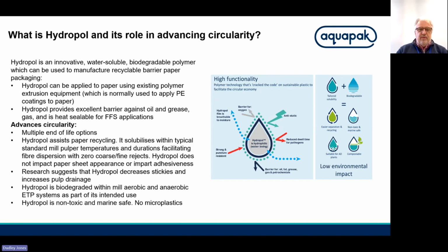So the tests have been done. I'll talk to you about that in a minute. But basically, it solubilizes in the typical pulper temperatures and durations. So within 10 minutes, it basically breaks down and it facilitates fiber dispersion. So you get a cleaner fraction when Hydropol and paper are put into a recycling mill. Once it separates, it's a much cleaner fraction than the PE. When the PE goes through a recycling mill, it takes some of those fibers with it. And I think a fiber loss in a recycling mill is around 5%.